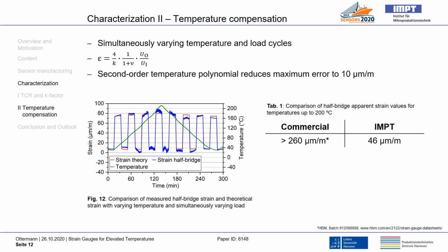The characterization procedure is shown in figure 12, where the temperature is increasing or decreasing all the time, and at the same time the strain cycles are applied, which would lead to a theoretical strain, which is shown by the red line. The blue line shows the measured half-bridge sensor signal with the second order temperature polynomial. As we can see, we have good accordance to the theoretical strain values with a maximum error of only 10 micrometer per meter.